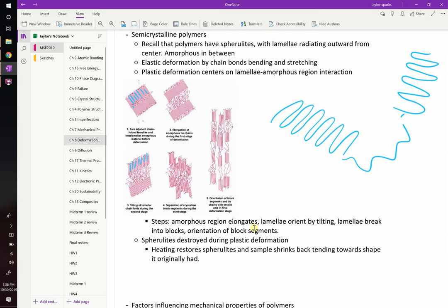So if it's a polymer that's not a network polymer, I'm going to say that's true, right? A network polymer is something like rubber or an epoxy, where remember we've added cross-linking agents to have it three-dimensionally bonded in all directions. This works really well when you have these amorphous regions that have rotational flexibility to be aligned. Then you see this strengthening, this work hardening effect. Okay?